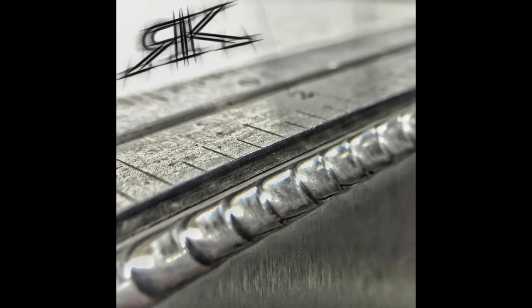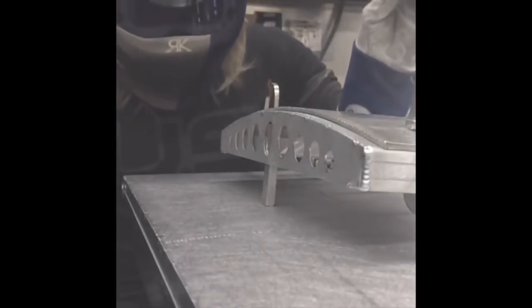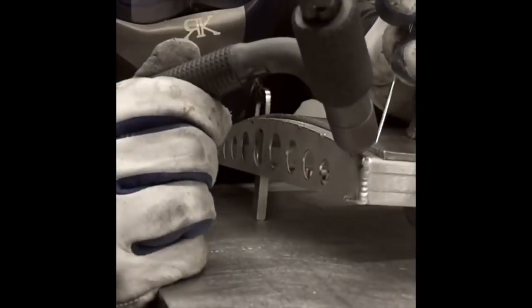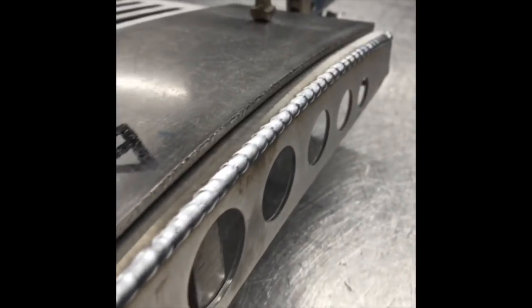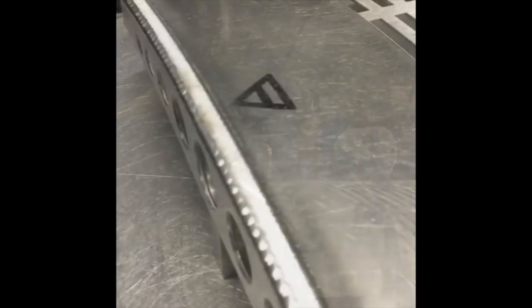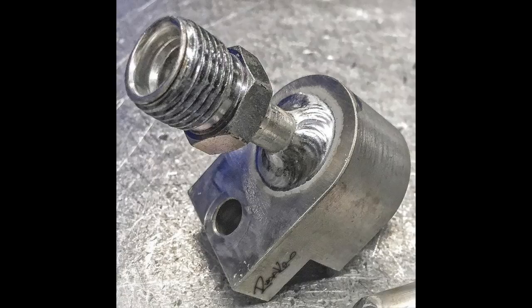We're talking details sometimes, like, in Rush's case, passing a helium leak test, but also maintaining the mechanical properties of the base metal, whereas if you use too much heat, you lose those properties. So he needs to be able to puddle real quick and weld it, and also not have a crater hole when he gets out of there. A lot of the stuff that Rush does not only requires passing a helium leak test, and of course a visual test, but he's also got to maintain dimension and maintain mechanical properties of the aluminum as well. If you put too much heat in and have to wait around for something to puddle, you start to lose mechanical properties with a wider heat affected zone and all that stuff. So these things like a little helium mix or active TIG gas can make a lot of difference for critical parts. And since I mentioned all that stuff, that brings me to the water-cooled fixture on that part.